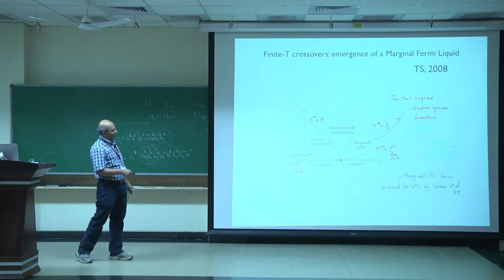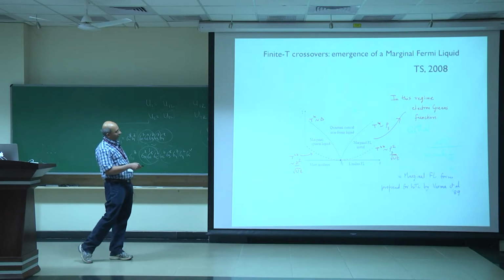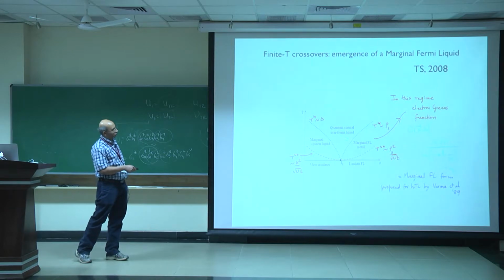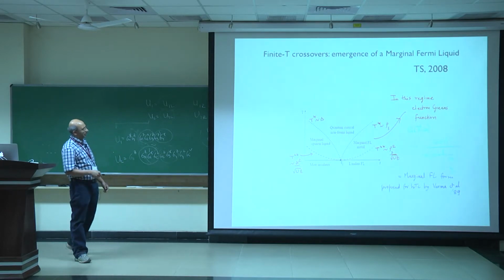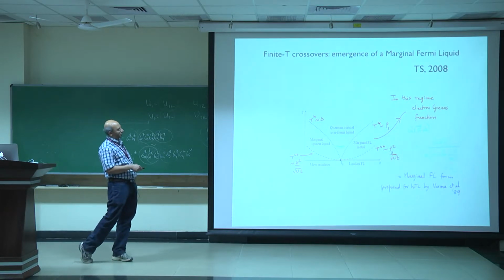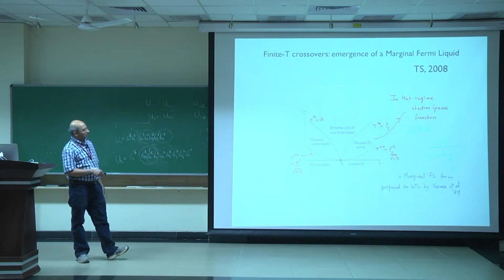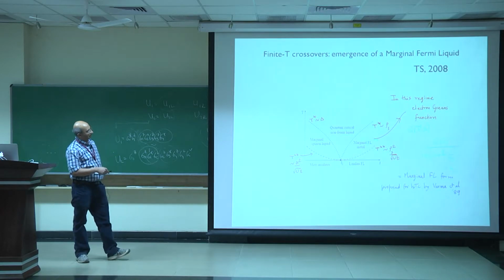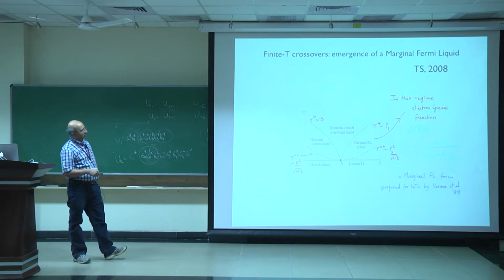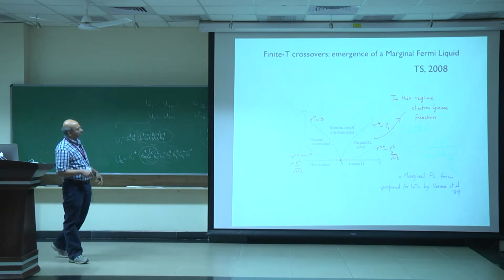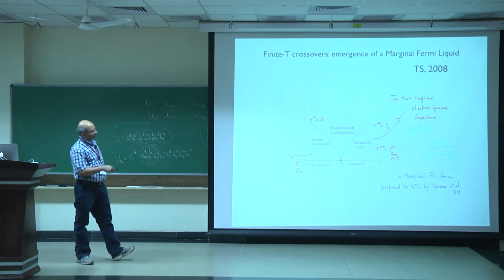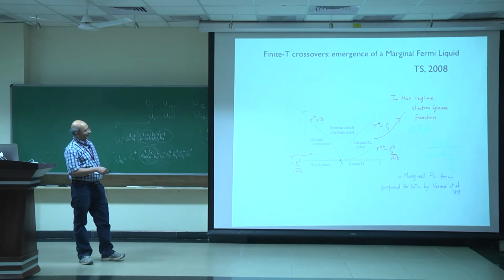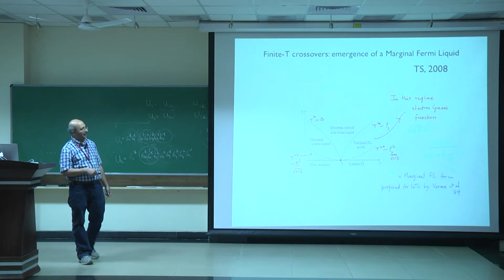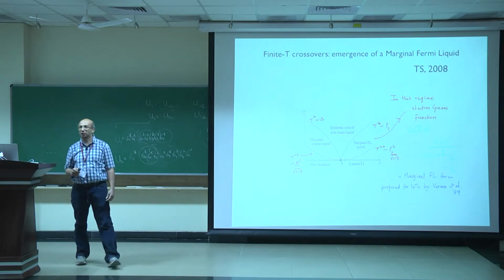There are two crossovers. If you're sitting right at the critical point and you go up in temperature, there's a quantum critical non-Fermi liquid. And then you ask, how does this cross over into the Landau-Fermi liquid if you're on the metallic side of the phase transition? And as I said, it turns out that the crossover out of the quantum critical non-Fermi liquid is not directly to the Landau-Fermi liquid. Rather, it first crosses over into a marginal Fermi liquid metal. It's called a marginal Fermi liquid because of the structure of the electron Green's function, which is precisely of a kind that was proposed phenomenologically many, many years back by Chandra Varma and collaborators. So it's a marginal Fermi liquid. And then eventually, at a parametrically lower scale, this marginal Fermi liquid gives way through a second crossover to the Landau-Fermi liquid. And loosely speaking, this is the scale at which the charge fluctuations realize they're no longer critical, and this is the scale at which the spin fluctuations realize that they're no longer critical. Okay?